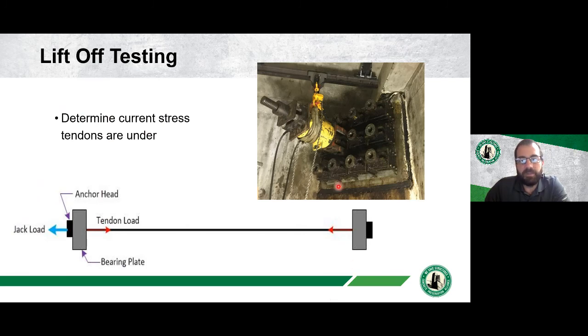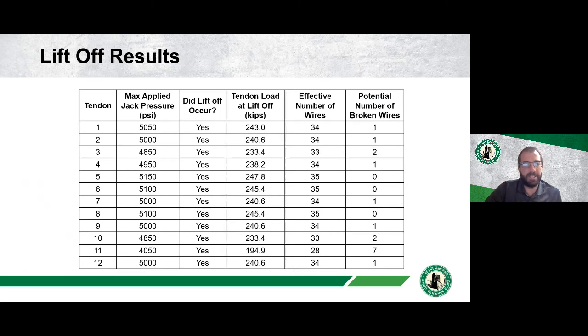So one of the things we did was load testing. So we did a lift-off test. We applied a jack at each anchorage, and we pulled the anchorage off. And when we applied enough load that the anchorage came off the bearing plate, then that told us what the tendon load was, so how much stress was in the tendon. And so here's the load jack that we used. Here you can see the jack pressure in PSI. And then we got lift-off. We converted that to how much load in kips we had.